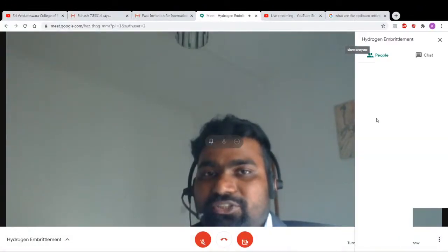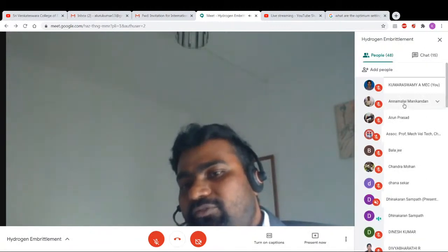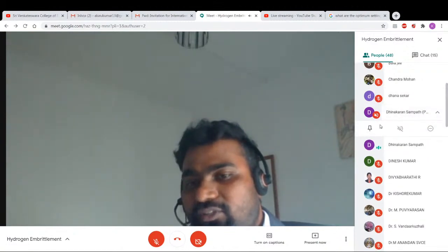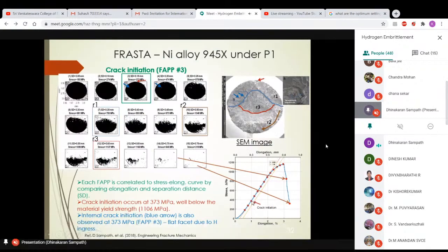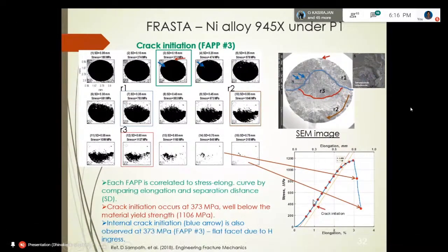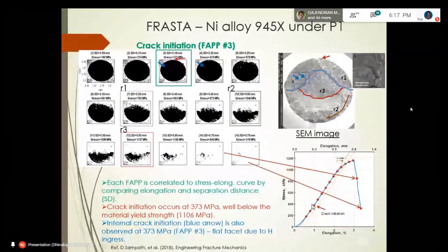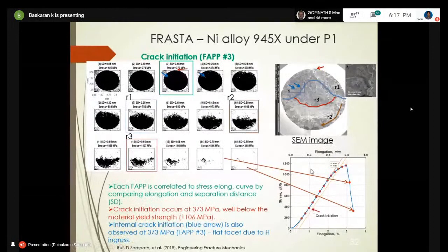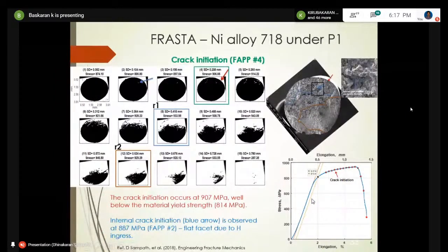So here we displace by a small value, in this case 0.05 millimeters each time. This is a uniaxial test, and we know how much displacement is needed to fracture it from the point of crack initiation. So what we did was we subtracted from the stress strain curve. This is converted into elongation, and then we backtrack and see where the crack initiated. The third fracture area projection plot corresponds to where the crack initiated. So what it tells us is the crack initiated in the elastic region of the stress strain curve. This is for 945X. It just failed in a brittle way.